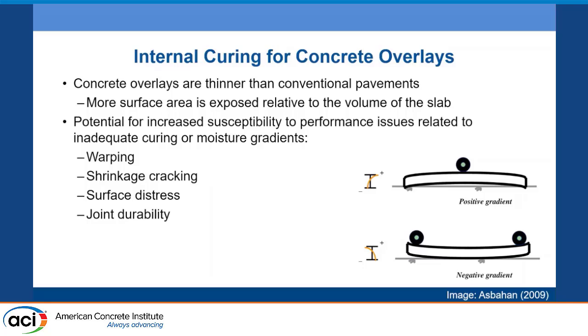And at least you have the potential for increased susceptibility to some of the types of performance issues that you might see if you don't get adequate curing, or if large moisture gradients do develop in the slab. In particular, what you see pictured here is warping. So if we do get a moisture gradient that develops in the concrete slab, warping can obviously cause the shape of the slab to change, and that could increase the roughness of the pavement, both right from the beginning and increasingly over its life.